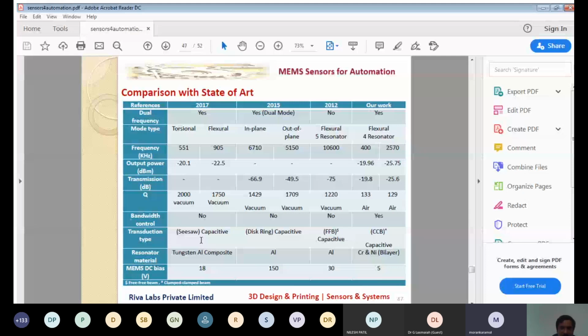So you can see the DC voltage: almost 5 volts was required as compared to 18, 150, and 30 volts. Then they used an aluminum structure, while we used chromium and nickel as a bilayer. Then there was capacitive transduction; ours was also capacitive. Ours was a CC beam, a clamped-clamped beam. Here it was a free beam. Then there were ring and seesaw types.